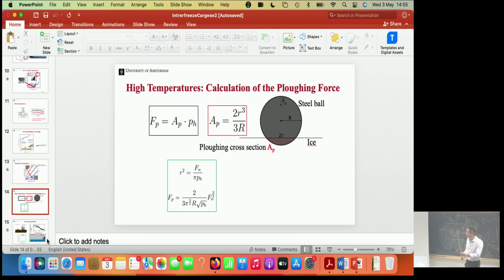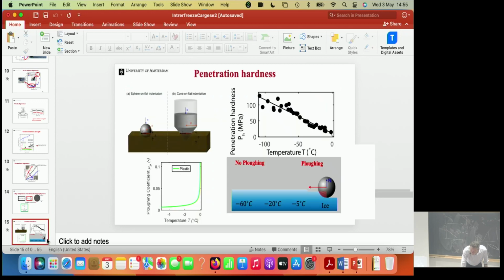And what I forgot to say, this is what we call the plowing force, which is the force that I need to drag the sphere through the material, and that is the contact area times the penetration hardness. That's a simple mechanics calculation. And so if we know what the penetration hardness is, we can calculate the friction force. And the penetration hardness is something you can measure.